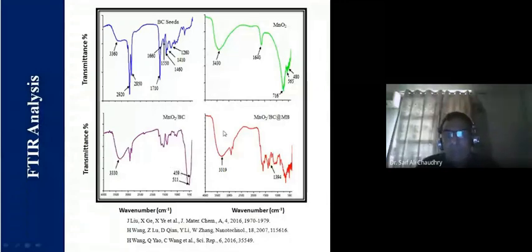Now when this composite was used as an adsorbent, we got broadening of this peak, and 3319, a slight change, because the OH group present on the surface of the composite has interacted with MB, methylene blue molecules. That indicates the interaction of the composite with methylene blue or any other dye, right?